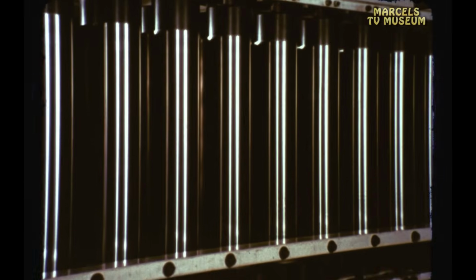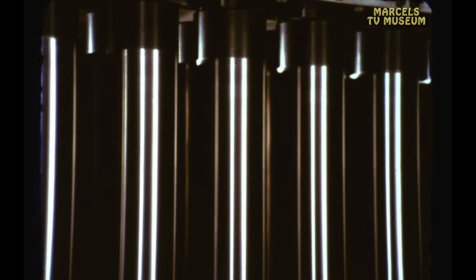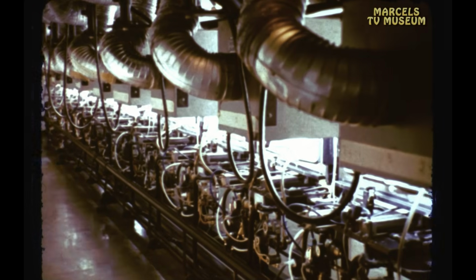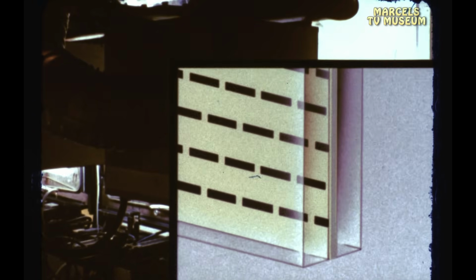Our shadow mask is made of soft iron, only 0.15 of a millimeter thick. The material is thoroughly washed. And then coated with a thin layer of photosensitive material on both sides. In this automatic exposure unit, the thin sheet of coated iron is sandwiched between two glass plates bearing the negative pattern of the shadow mask. Both sides are exposed to ultraviolet light.